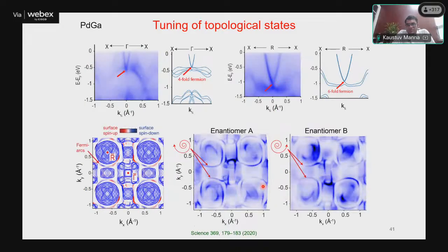Now the experiment. So first we had to prove that this palladium gallium has fourfold and sixfold degenerate band crossing at the gamma point and R point. And with the ARPES spectrum, we have proved yes, we have the fourfold and sixfold band crossing, as well as the Fermi arc. As you can see, we have the Fermi arc. Now, if you go from left-handed chiral to right-handed chiral, you see, this is simply a mirror image of each other. If one is left-handed, the Fermi velocity is like this. When we go from left-handed to right-handed, the Fermi velocity is simply opposite. That means by controlling the structural chirality, we are controlling the topological states in momentum space. This is the direct experimental proof of that.